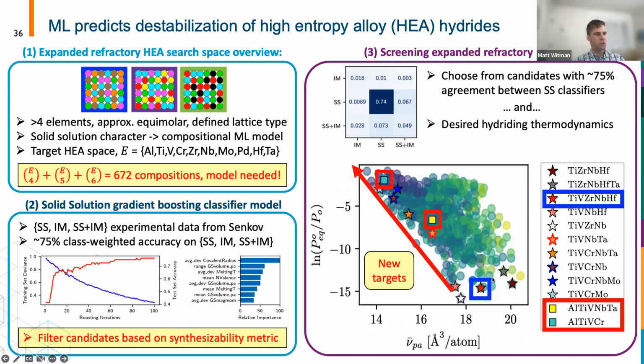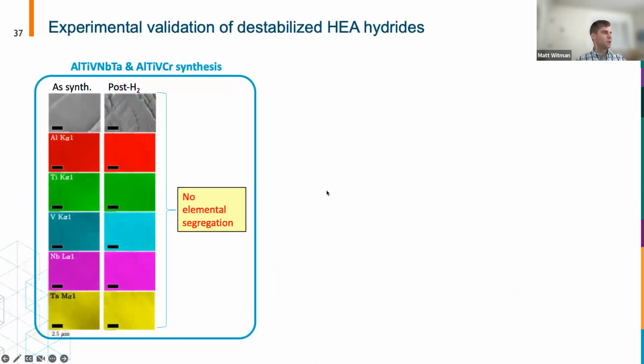In blue is the original high-entropy alloy hydride discovered, which is actually one of the most stable in the data set. And so you can see how many orders of magnitude this data set is predicted to span in terms of this thermodynamic stability. And so we chose 2 aluminum containing compounds that span the entire distribution of the predicted pressures. And so we went in lab and made them with our collaborators.